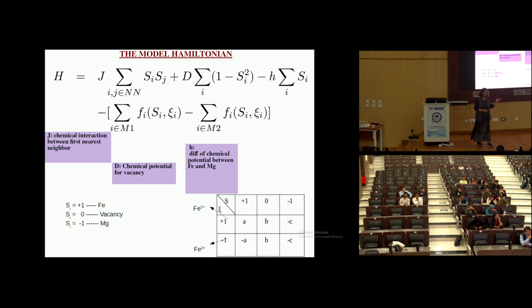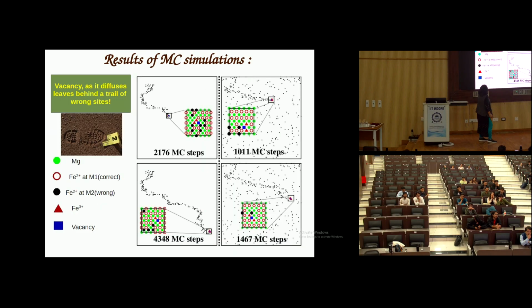So the three species are iron, magnesium and vacancy. So then I have to consider a spin 1 system. If I have a spin 1, then the corresponding states are 1, 0, minus 1. So I have 3 states. So instead of a 2 state, now I have a 3 state Ising model. And as you can see, the Hamiltonian looks much more complicated. And then we did the same molecular dynamics, and the result was fascinating.